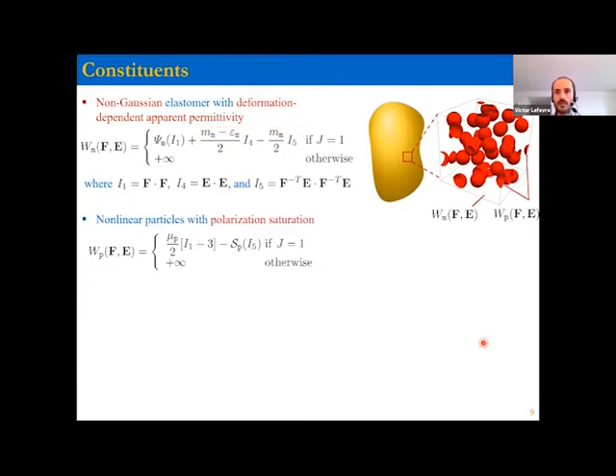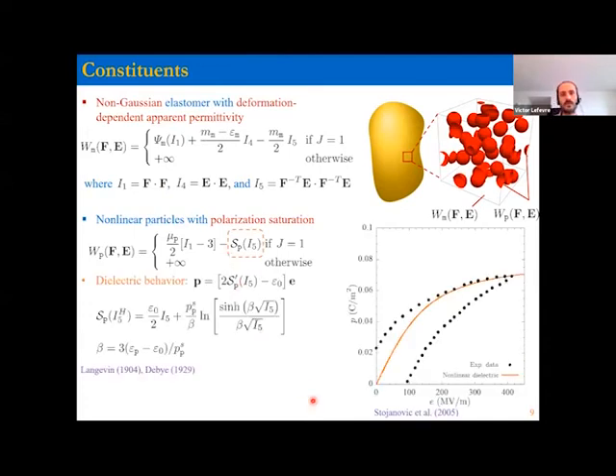That's for the matrix. For the particles, they're going to be nonlinear with polarization saturation of their polarization. So the elasticity is simply Neo-Hookean. And then we have this function S P that you can use to describe any dielectric behavior for the particles, in particular saturation of the polarization of ceramics. And so that's a typical choice that we make to do that. And again, the agreement is not perfect, but it gives a good idea of what's going on.